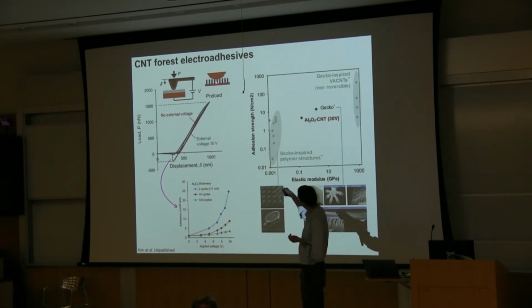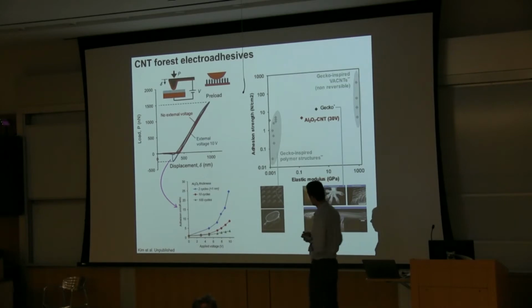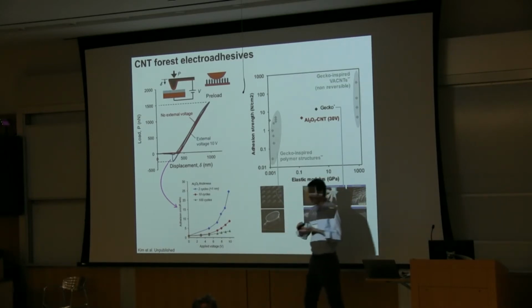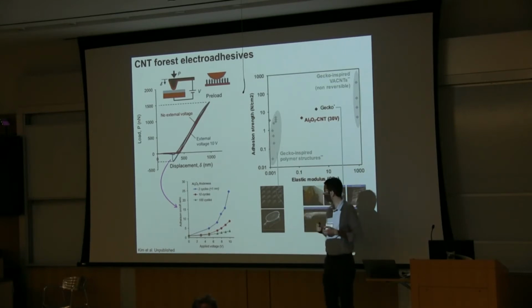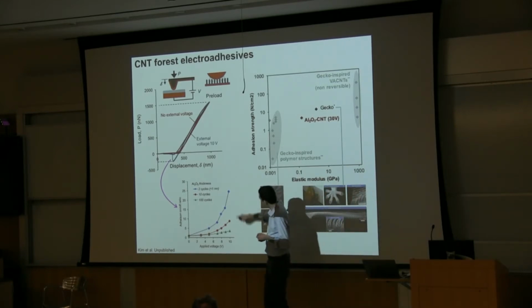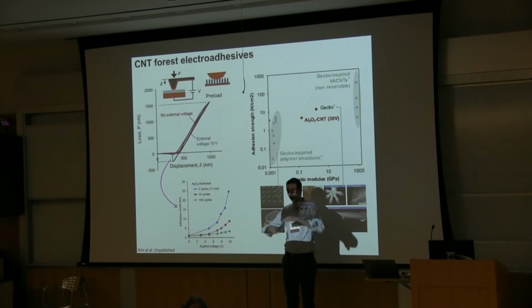And therefore, you get opposite charge between the coated nanotubes and the tip, and you do a mechanical test and compare a test without a voltage to a test with a voltage, and there's a significant pull-off force when the voltage is applied. Maybe obvious from a physical point of view. Basically, we're studying how to engineer these surfaces, their compliance and their roughness to enable a very high on-off adhesive ratio when we apply this voltage.